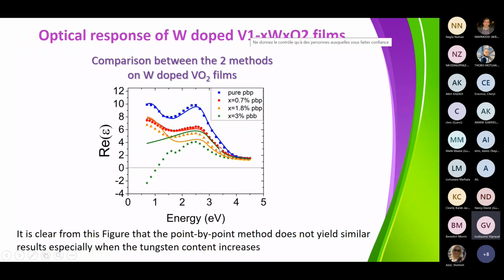So the real part, you see, with the point-by-point technique and with the standard method: the point-by-point is the markers, and the full line is the standard method. For pure, very similar. For 0.7%, very similar. For 1.8%, you begin to see a discrepancy. And for 3%, it's completely different. Okay? So it's telling you that if you try to describe the refractive index by the standard method, and by any chance you have a mixture of phases, or you think that you are in an insulating phase but you are in a metallic one, then you are completely wrong.